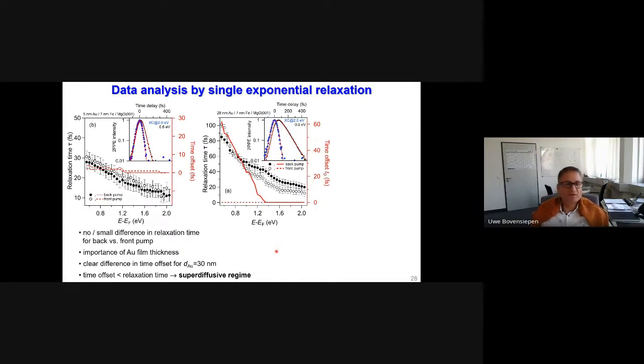Okay, so we fit the data by a single exponential relaxation convolved with the cross correlation of our laser pulses. So this works pretty well. You can see here for the two thicknesses, this is the thicker gold layer, 28 nanometer, and this is 5 nanometer of gold. And then we analyze the delayed start of the relaxation. This is the red data, which we refer to as the time offset, and the relaxation time tau,